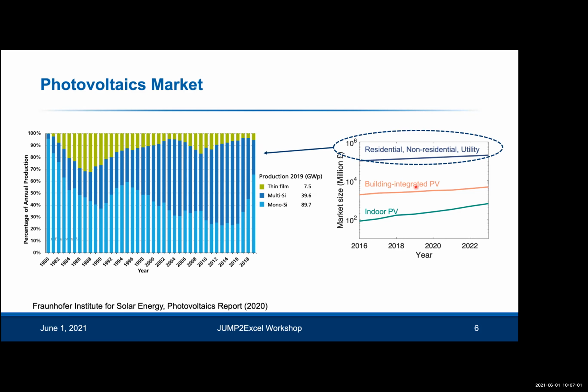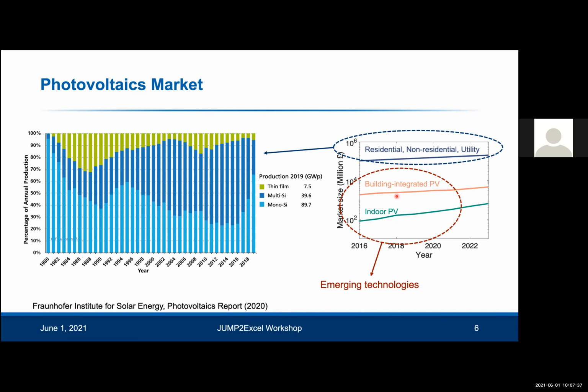But there's also other markets as well, which are also growing rapidly. For example, there's photovoltaics used for building claddings, as well as indoor PV. And you can see that the slope on this log linear plot for indoor PV is a lot higher than for these other sectors here. So although indoor PV is relatively small right now, it is a fast growing area and has an annual compound growth rate of 70%, which is a lot higher than for residential PV. And for these two smaller markets, you can still use silicon and cadmium telluride, but there are actually a lot of advantages to using emerging technologies. And this is where the new materials that academic groups such as my own group are developing can play quite a significant role.